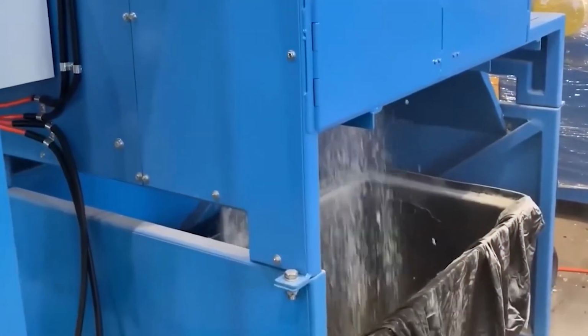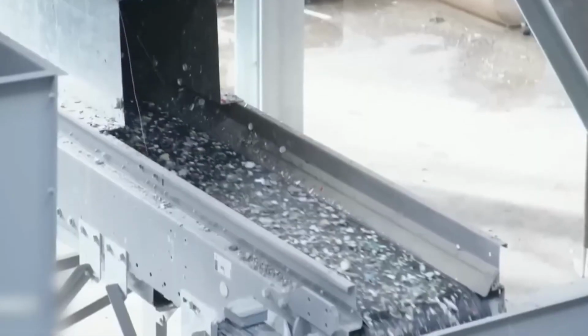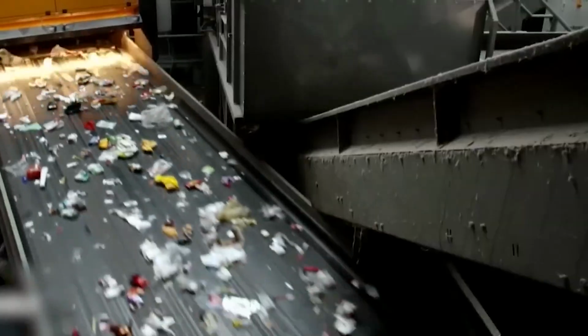Once material reaches acceptable purity, it passes through high-speed grinders where blades rotating at thousands of RPM reduce plastic into uniform flakes. This flake shape isn't random. It increases surface area compared to bulk plastic, reducing energy consumption by 40% during thermal melting.